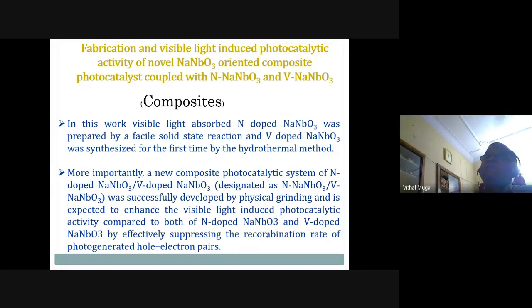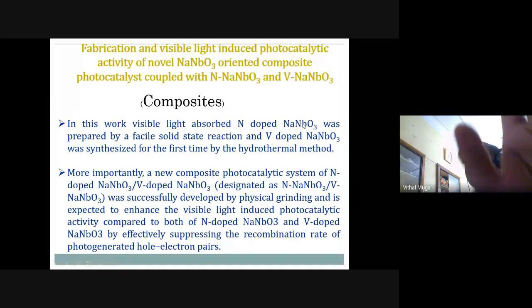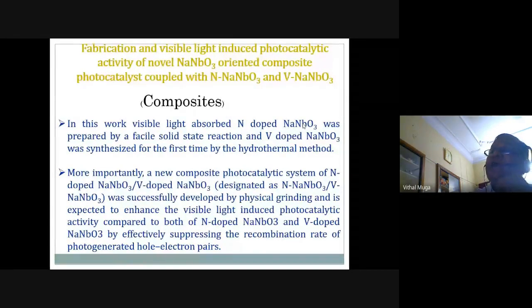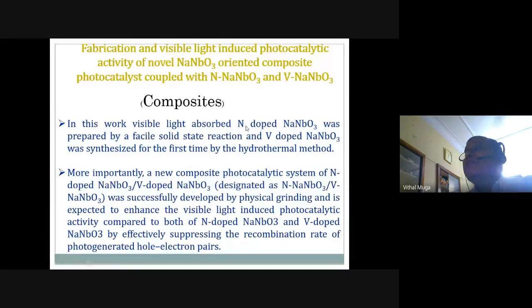Then I move on to another one where, I told you that Z scheme photocatalysts or heterojunctions will help in accelerating the photoactivity of the materials. Now, what we have done is we have prepared N-doped NaNbO3 and V-doped NaNbO3. Now, N goes into the oxygen site, V goes into the Nb site. Please remember this. So N-doped NaNbO3 can be prepared by taking NaNbO3 and heating it around 400 in the presence of urea, or in the presence of ammonia gas passing for 2 hours, you will get nitrogen doped NaNbO3.